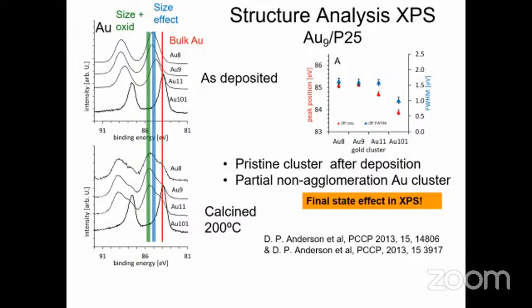It means that the cluster itself is reacting on the charge state when the photon hits, and it has a period of time to get a relaxation. And this relaxation is actually a fingerprint of these different clusters. On the peak of the gold itself, if you're looking for the bulk gold, usually it's 84 electron volt, the binding energy. While we saw a shift of this 84 to a higher binding energy, and this is related to the final state effect of every single cluster.